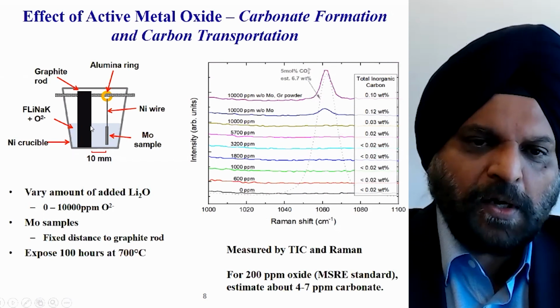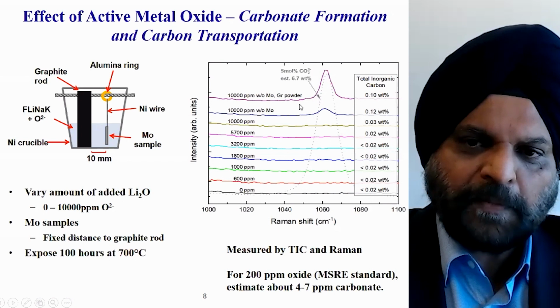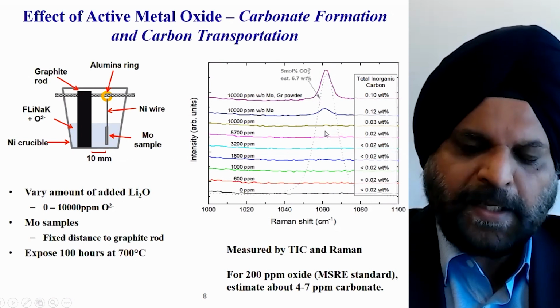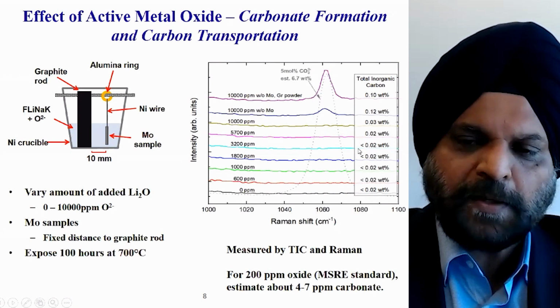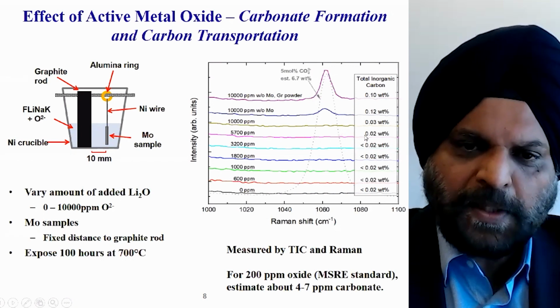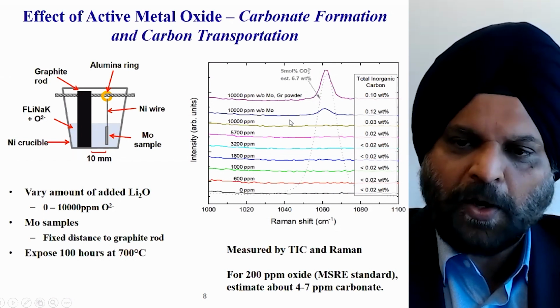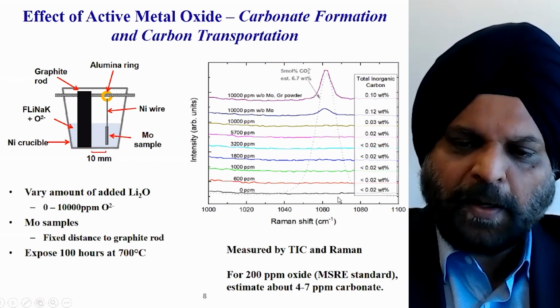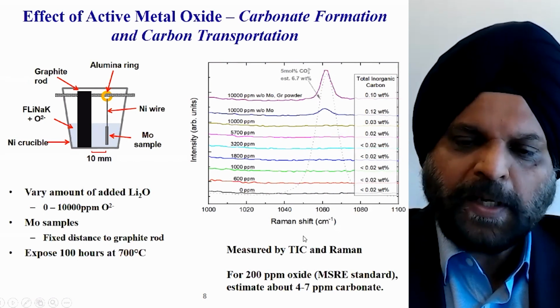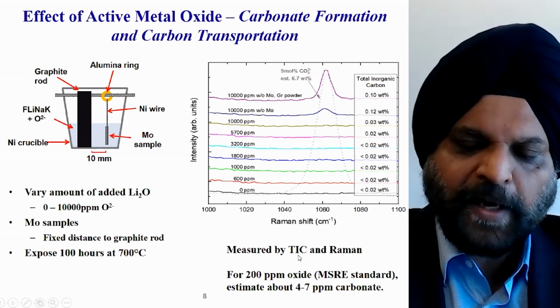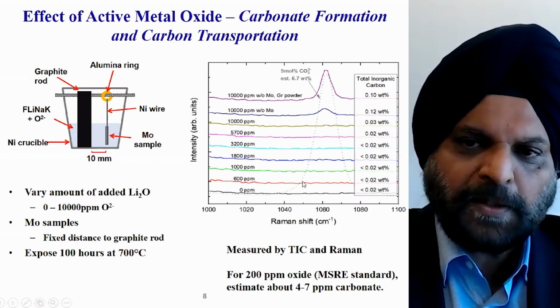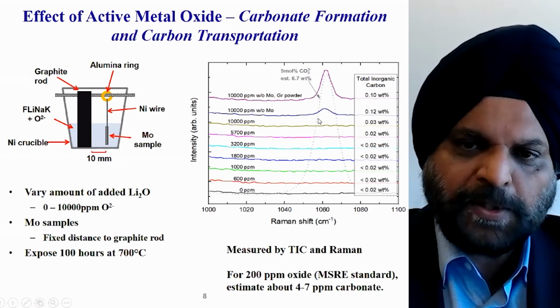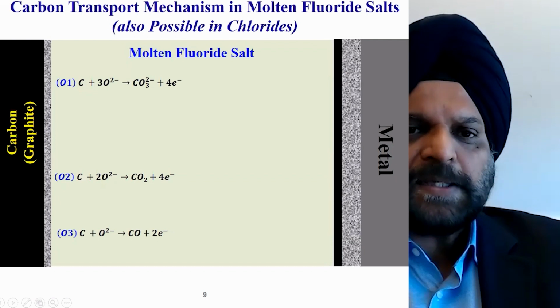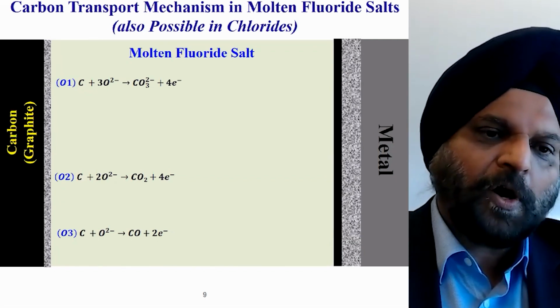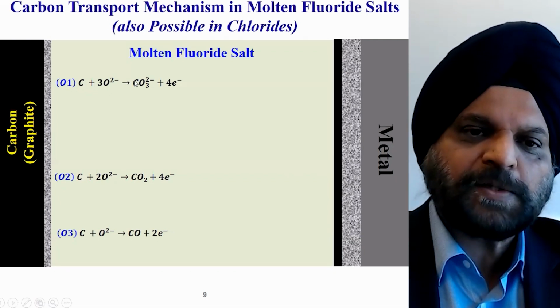Yes, we actually saw carbonate peaks in the FLiNaK where tests were done, especially when we increased our concentration of oxide significantly. We tested both Raman as well as total inorganic carbon in FLiNaK, and that inorganic carbon was in the form of carbonate. And you can see that carbonate peak, which is shown here. In this case, carbon can be transported from graphite to the metal surface just by impurities.